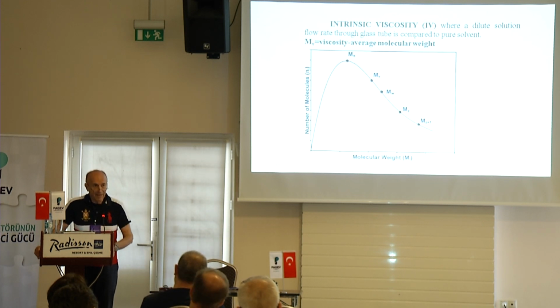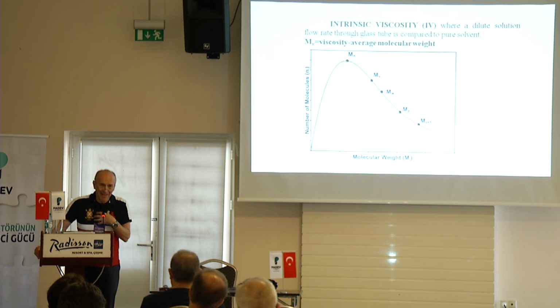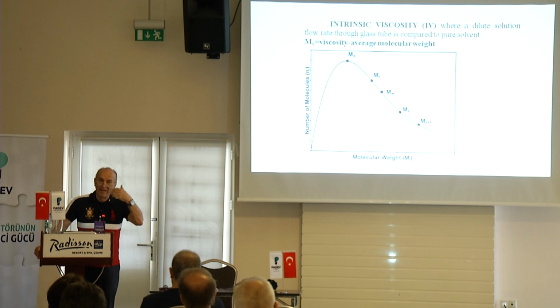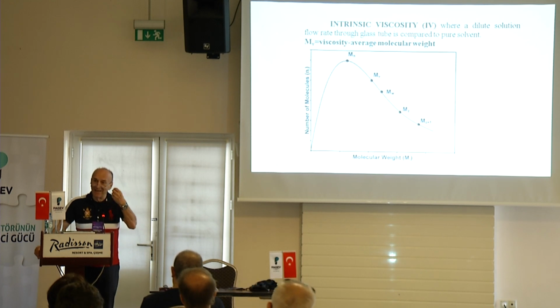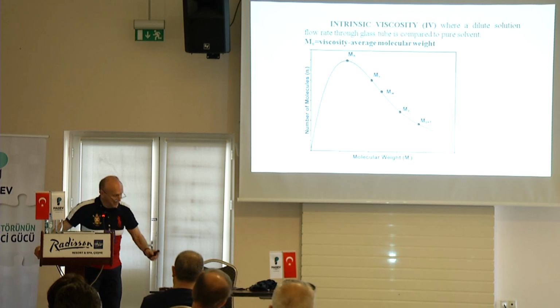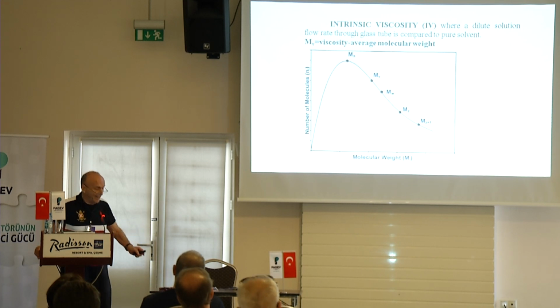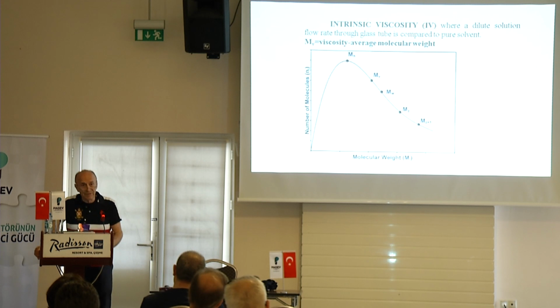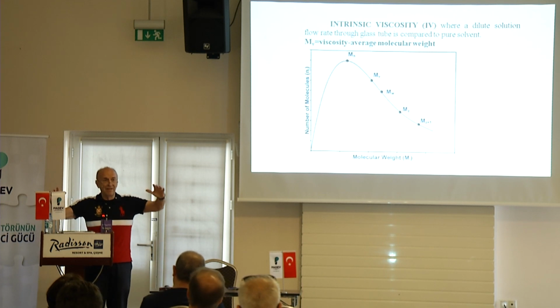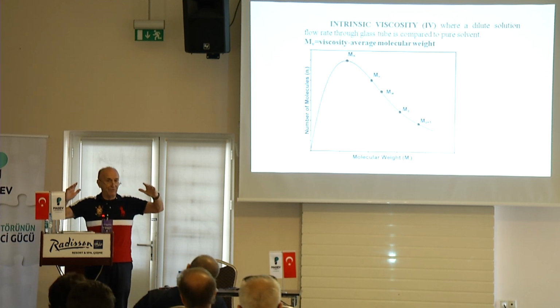However, some people, like me, I'm old, and so my age, when squared, will have a heavier weight, so this is called the weight average, and the weight average will be shifted to that point. And then you can take a cube and so forth, and you have the other averages of the molecular weight. So these higher averages tell you about the breadth of the molecular weight distribution.